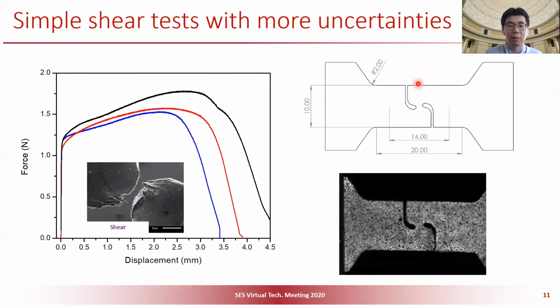And we also did the simple shear test. The test sample is really small, and there are only 6 to 8 grains in the smallest cross section. So we observed more uncertainty in the force displacement curve. We also did the DIC measurement of the strain, and we processed the strains according to the DIC result. What is really interesting is that compared to those tensile tests, in the shear tests, as expected, there is no necking. The material really just hardens, right? That's because there is no reduction in the gauge length or the gauge area. There is no way to neck, right?